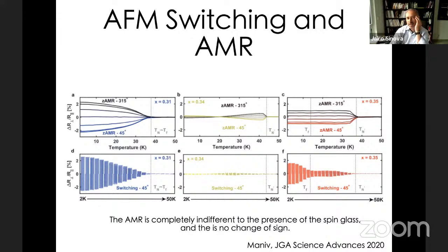Like, one of the things that they did in the experiments of the low currents on the manganese gold and particularly the copper manganese arsenide is to look at XMLD to see that the switching of the domains at the low temperature, seeing clearly that you go from 90 degrees switching. Once you go to the higher temperatures, then of course the switching is just not related to this Néel spin-orbit torque. And here, it's not so clear that in your case it would be related to the Néel spin-orbit torque. But now you've clearly shown that it's connected to the magnetic structure, having those two types, which was the new result that I didn't know.